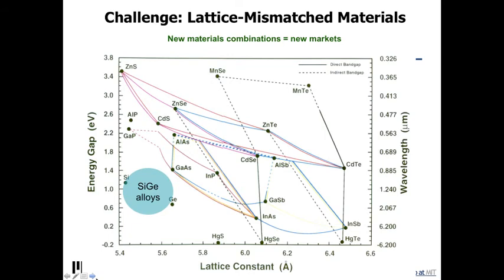So this is the overall lattice mismatch between different semiconductors, and this is good because first of all it shows you why silicon germanium was important. It also shows you why, if you solve this problem, you could put a lot of different materials with a lot of different functionality into manufacturing on silicon. So what this says is that the lattice constant of silicon, that square that I was talking about, the base unit cell is 5.4 angstroms, right? And the band gap shows what kind of light or energy it can interact with. It does other things too, but that's basically one of the things it does. And over here is germanium, which you'll notice is the same lattice as gallium arsenide.